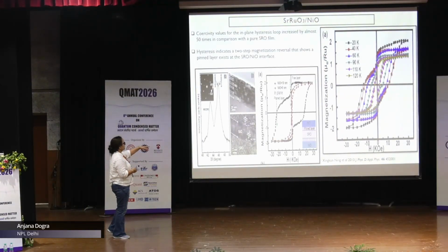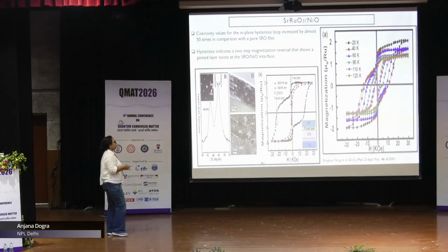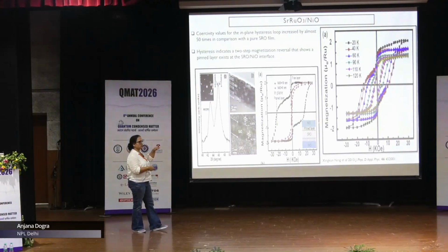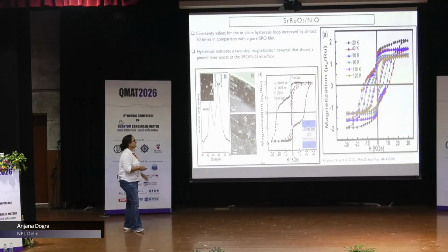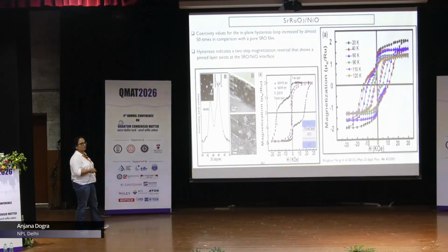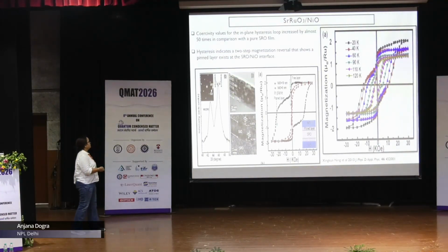This is what I was telling: the step-like behavior in hysteresis has been observed by people in SrRuO3/NiO, where they have correlated it to pinning. They discussed that the layer of SRO is pinned between the NiO layers. So this pinning effect is happening in these kinds of systems, and that is why this step-like behavior is observed in the hysteresis.